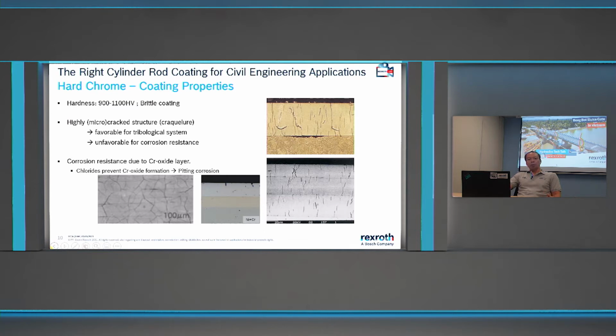And if you put the coating under a microscope, you can see the micro crack structure, which is good for the tribological system but unfavorable for the corrosion resistance. Because you know, the corrosion resistance is due to the chromium oxide layer, and the chloride in the environment prevents the chromium oxide formation, so you have pitting corrosion.